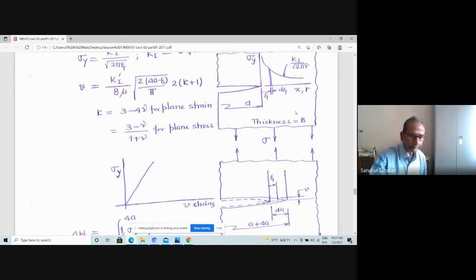I want to repeat this point. This is called the reverse argument. Although it is an irreversible process, Irwin treated it as a reversible process. If the crack got extended from A to A plus delta A, then you have this displacement and it has become stress-free. But if you want to bring the extended crack back to the original crack, that is A plus delta A to A, then I have to eliminate this opening.